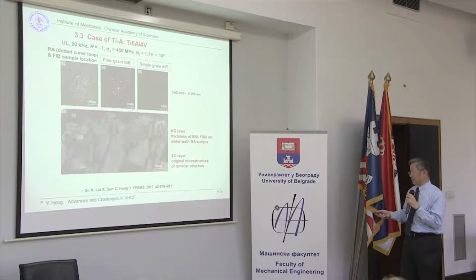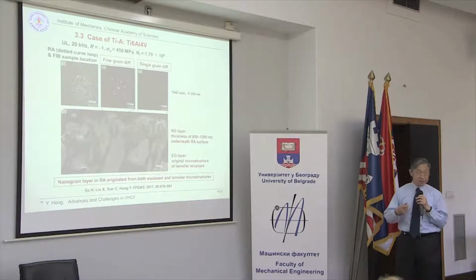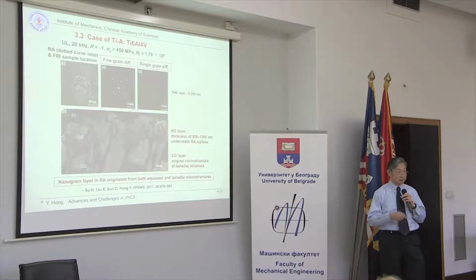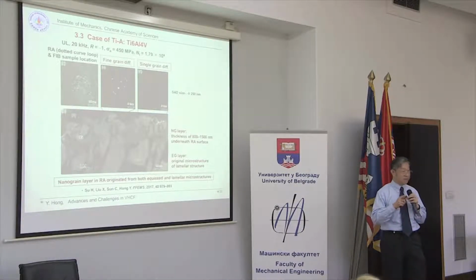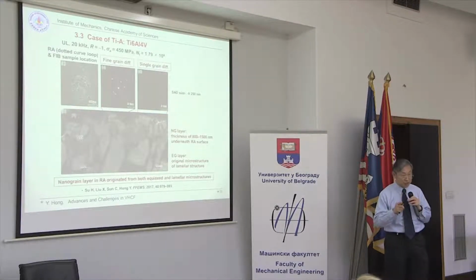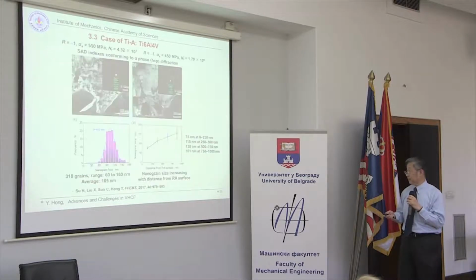And the thickness is 800 to 1500 nanometers. And we said for titanium alloys, there is also a kind of nanograin layer underneath the fracture initiation region. And also we measure the average grain size in this region is about 100 nanometers.